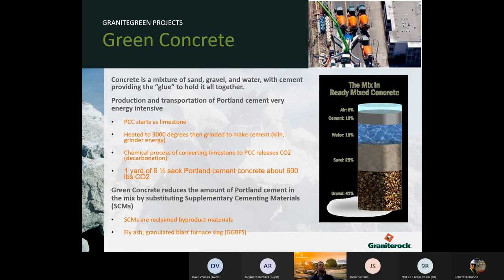Here's a composition of concrete, like we talked about: air, cement, water, sand, and gravel. Production and transportation of Portland cement is very intensive. How we talked about cement being made, the energy required to heat the kilns that make the cement is so high that a lot of the CO2 production is from the energy required for that. The other component is when the limestone is heated up, it actually releases CO2. So that is a huge component of it.